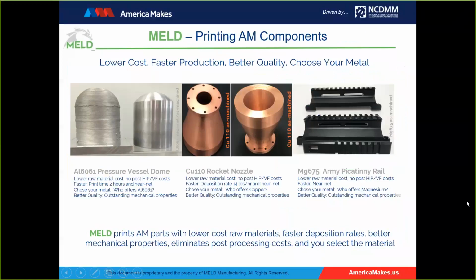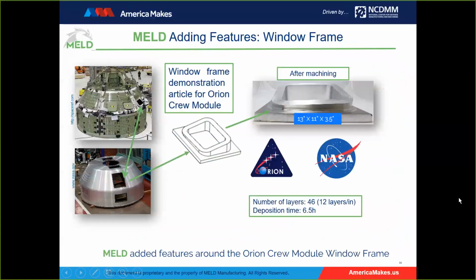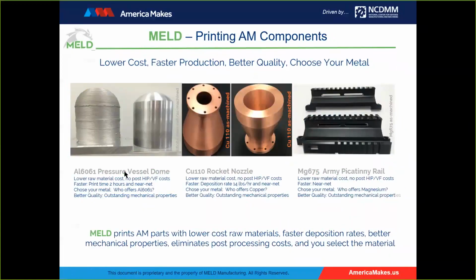Well, then in coating and repairs, another application is components. Here's an aluminum 6061 pressure vessel dome. It's got a 2-inch diameter hollow insert, about 1 millimeter layers. Near net machining, that's just a handful of mils to machine it to near net shape.